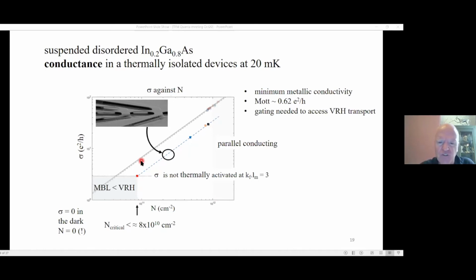The conductance is not thermally activated. We're slightly above where the Mott minimum metallic conductivity is. So they are metallic, they're not going into this variable range hopping region yet. And that's because we've illuminated. So we've got a 0 conductance in the dark, but it's because we've got no carriers in the system. The critical carrier density is about 8 times 10 to the 10 when you illuminate in this system.